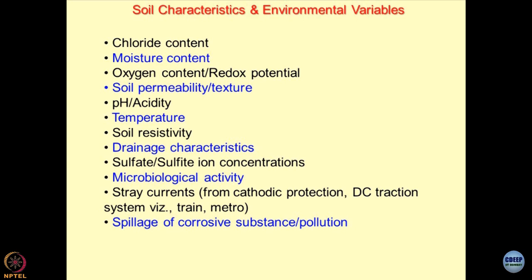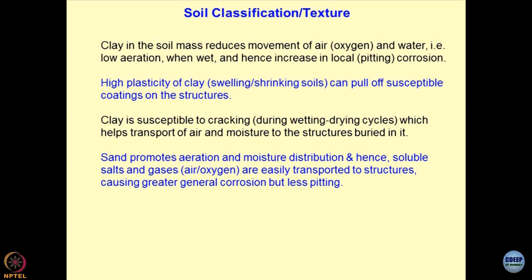This is a very complicated subject and not much research has been done in the Indian context, but it is of great importance to the industry. Soil classification and texture is the most important factor because everything is linked with it. The presence of clay is a big deterrent as far as supply of oxygen and water is concerned. Low aeration when soils are wet would increase pitting of pipelines because of bacterial activity. High plasticity clay minerals — swelling and shrinkage — also become a big issue.